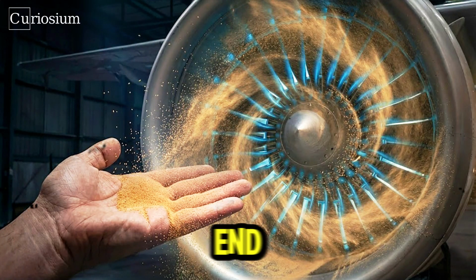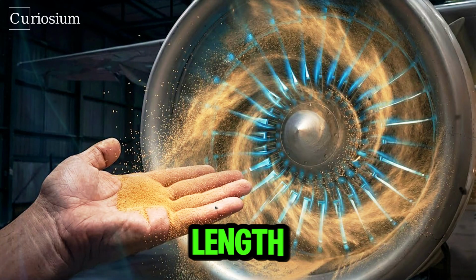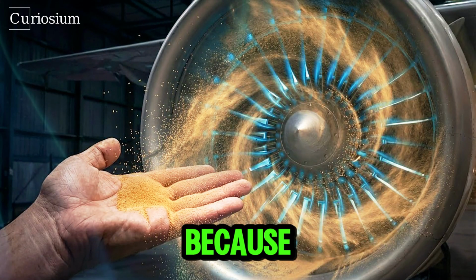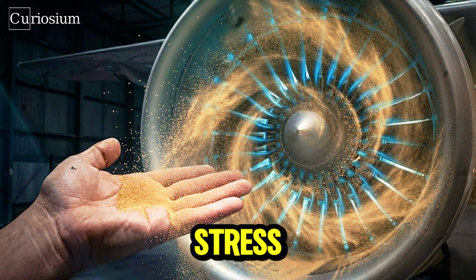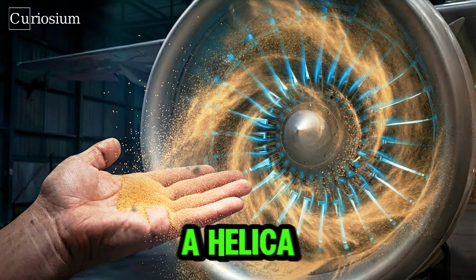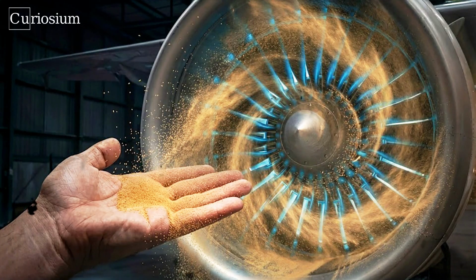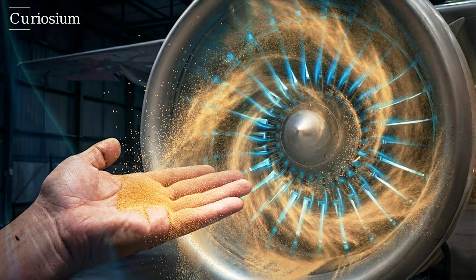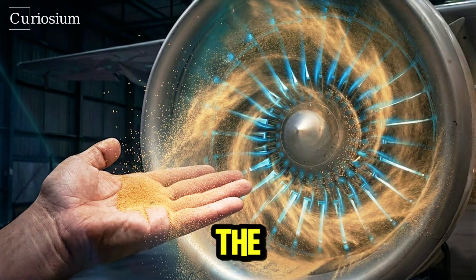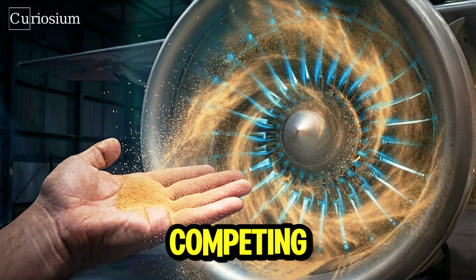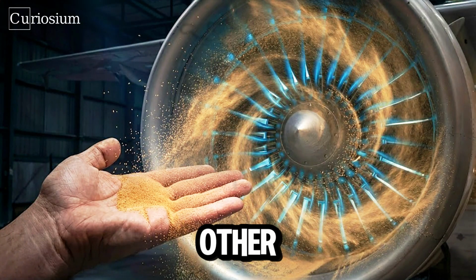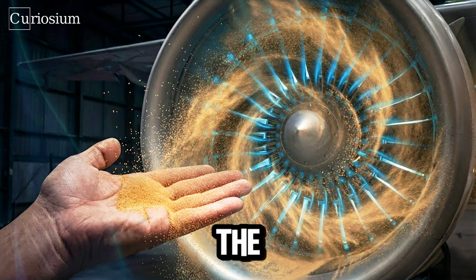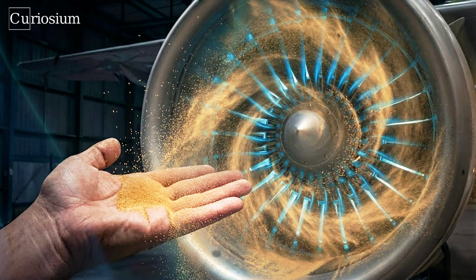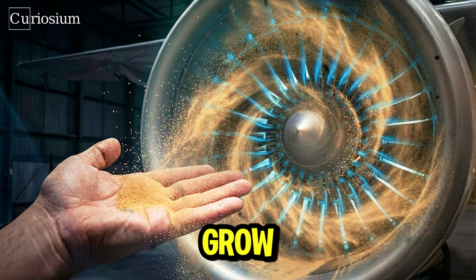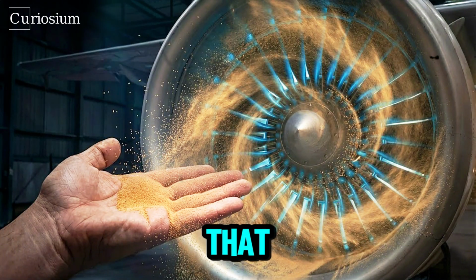If you stopped here, you would end up with many long columnar grains aligned along the length of the blade. That is already an improvement, because there are fewer grain boundaries cutting across the main stress direction. But engineers discovered that by adding a helical passage, a spiral often called a pigtail, just above the chill plate, they could go even further. As the solidification front moves through this spiral, many of the competing grains are blocked by the walls or by each other. Only one grain, oriented just right, makes it through the entire spiral and into the blade section. Above the pigtail, that single crystal continues to grow, filling the whole blade. The result is a part that behaves, from a mechanical point of view, like one giant crystal.